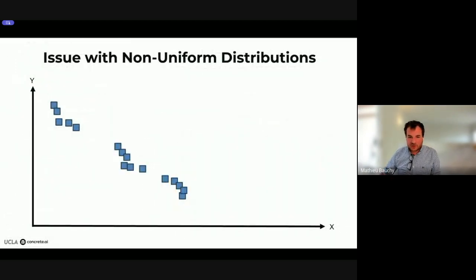Okay, so then there is a distinct issue that's specific to concrete, but also for materials in general, which is that typically we work with distributions that are not uniform. And so that creates some unique difficulties when it comes to using machine learning, because, for example, if you take a typical cross-validation approach, where you would randomly split your training set into a validation set, when you have those non-uniform distributions, you can have some models that are actually obviously overfitted that will fit the data very well and will give you a very good validation score.